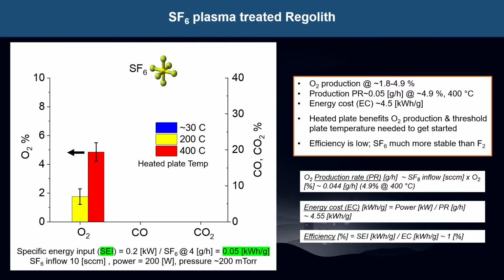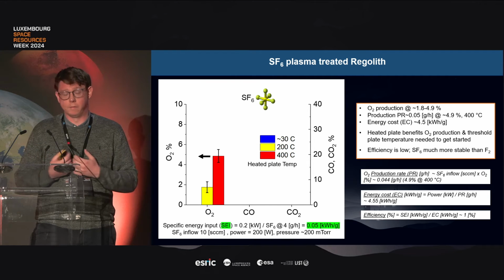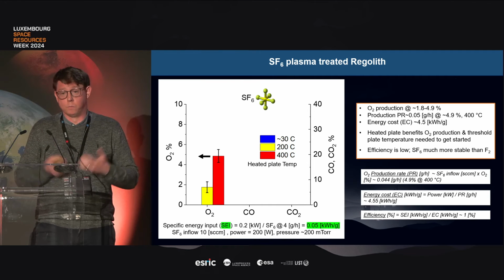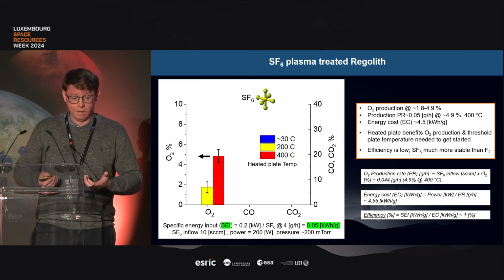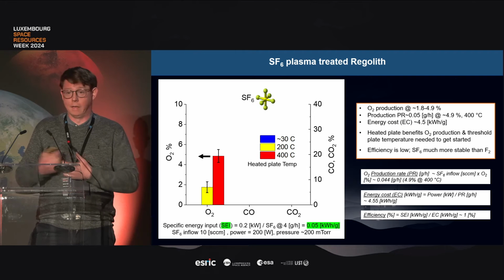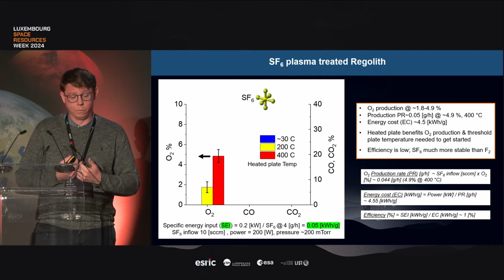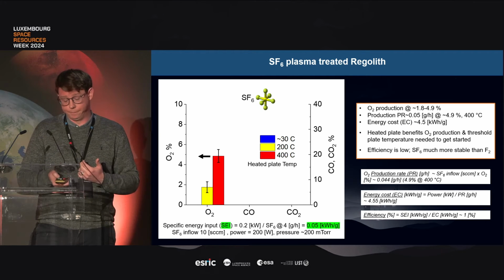Looking at the energy cost, it's the order of 4 kilowatt hours per gram. So taking that energy cost and comparing with the specific energy that's input, I can get an idea of the efficiency for this kind of conversion. And of course, this is not optimized. There's a lot of wasted volume in the plasma, for instance. But the efficiency is around 1% for this. Now, SF6 is much more stable, and that's its benefit. That's why it's being used rather than fluorine gas. So we'd expect these kind of values.